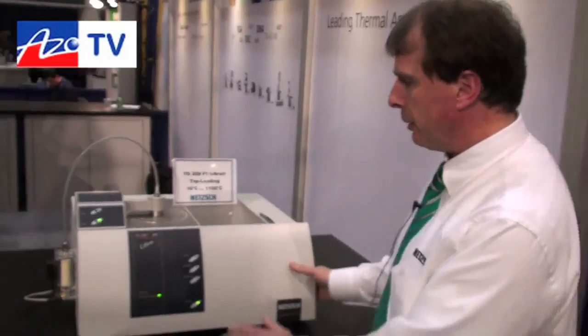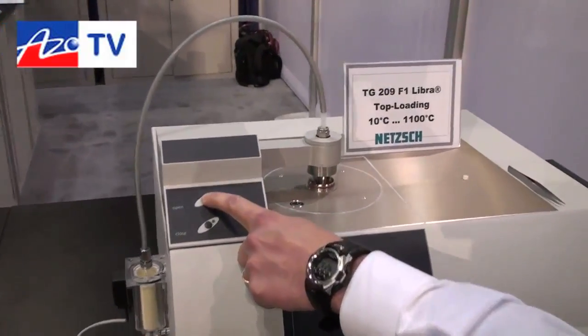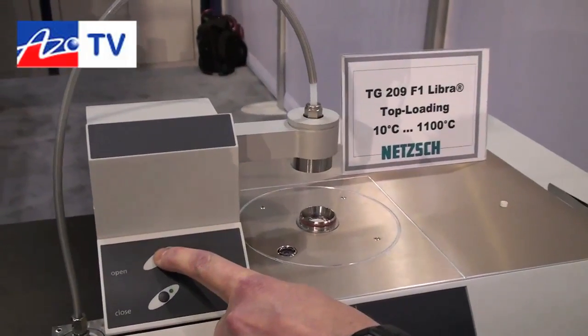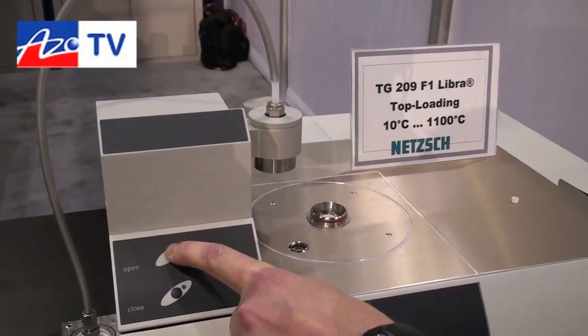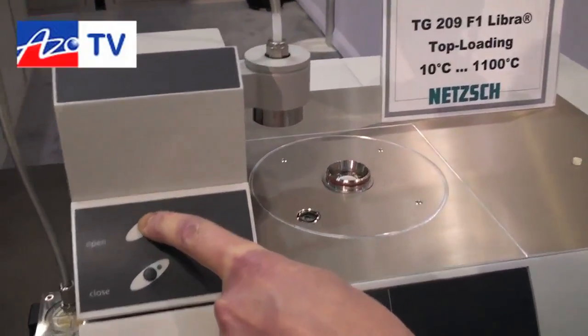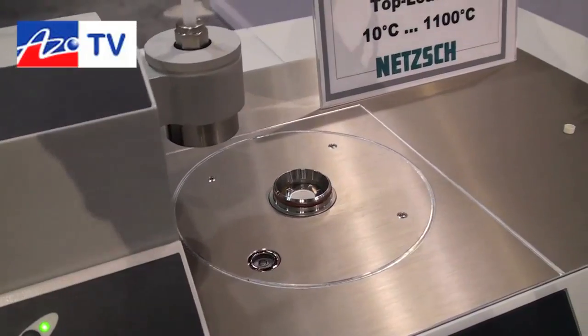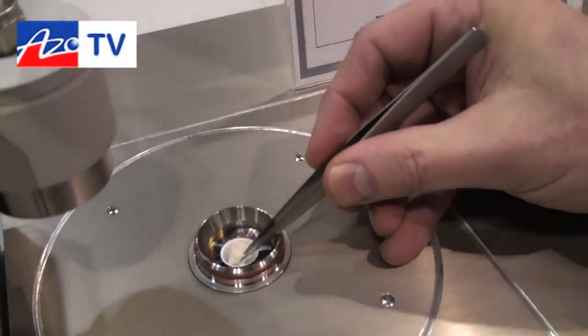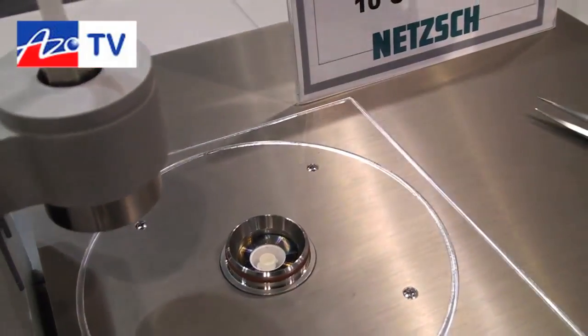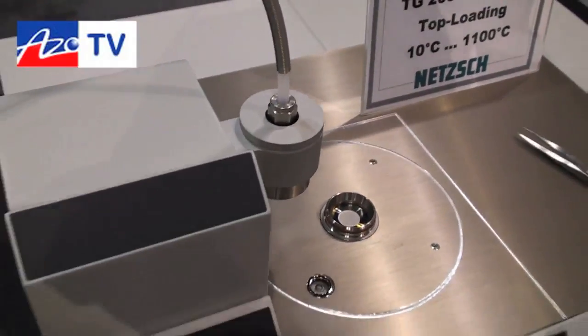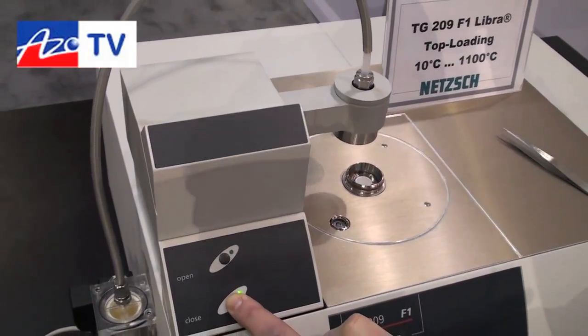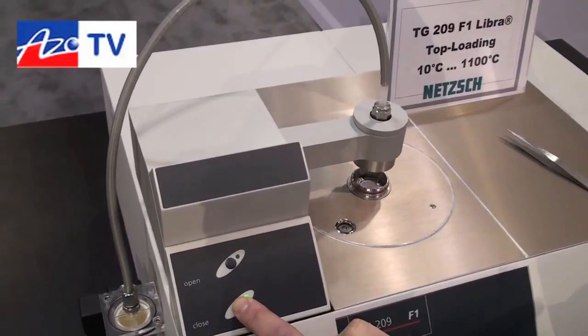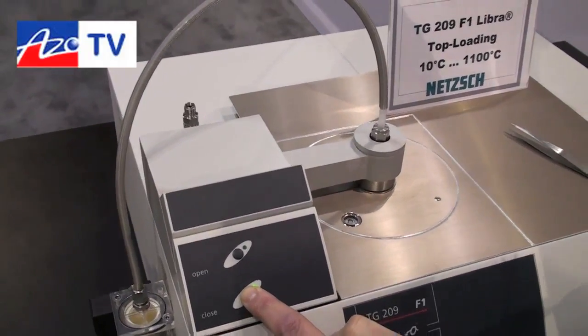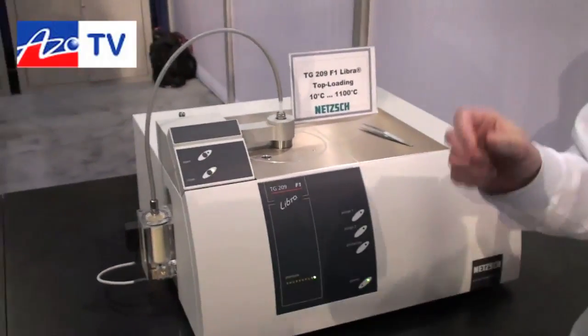Okay, loading the sample is very easy in a top loading design. As you can see here, all I need to do is open the top, and the sample carrier now comes up to the top of the furnace. I can then load the sample very easily, and just by 2 buttons, close the furnace. So there's no fragile hang-down wire, there's no horizontal beam that can break, and when you're loading the sample, the carrier is actually disconnected from the balance, so you cannot damage the balance while you're loading the sample.